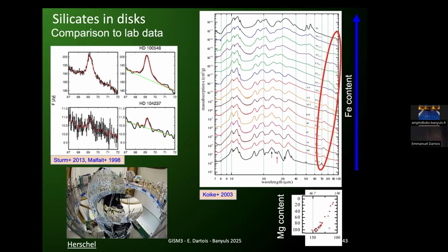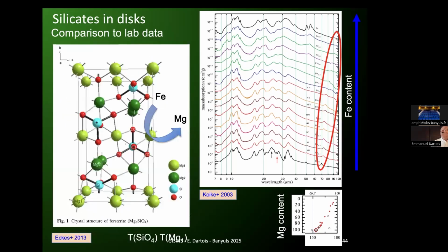This was the case for a few sources, and basically using Herschel, it was possible to show that in many of the disks observed, you were almost always dominated by a magnesium-rich silicate. So it doesn't mean that you don't have iron, but if you have iron, it might be in another phase if it's in the solid form. So basically, this is what is shown here. You replace iron by magnesium and you see a shift.